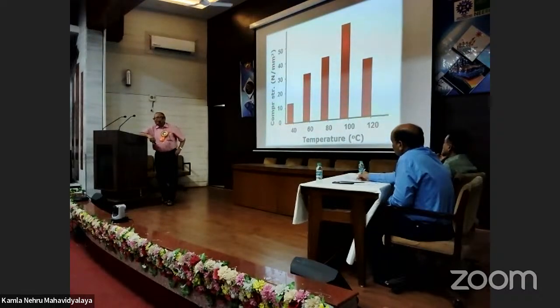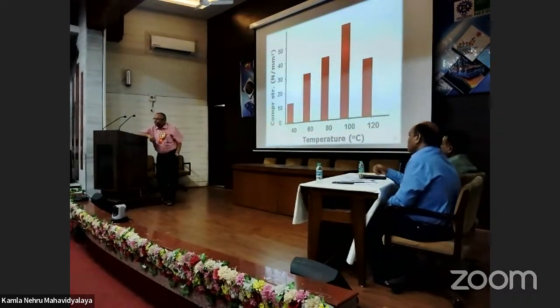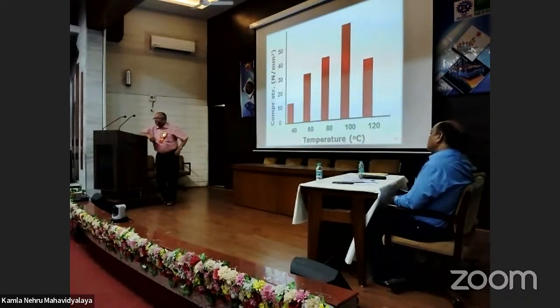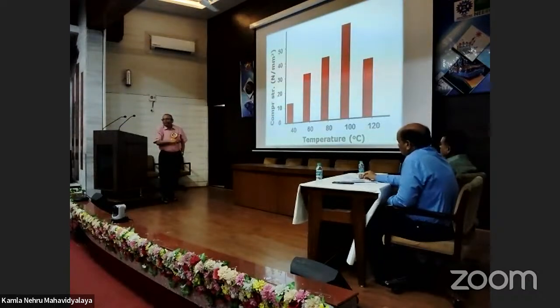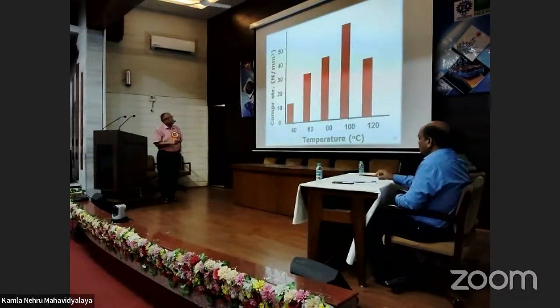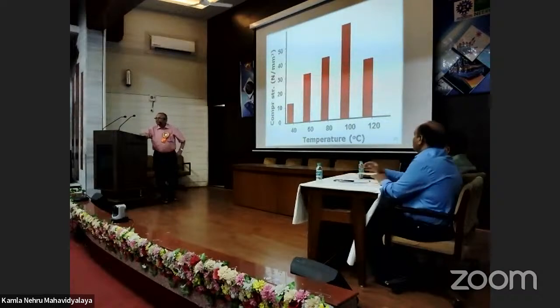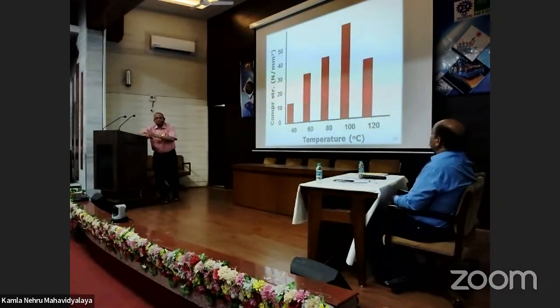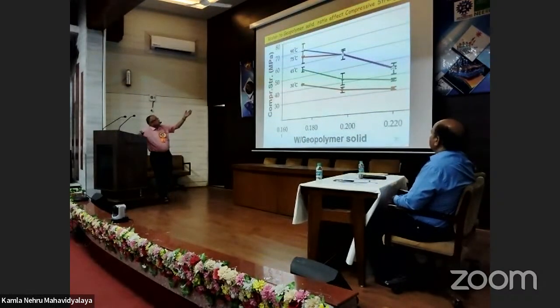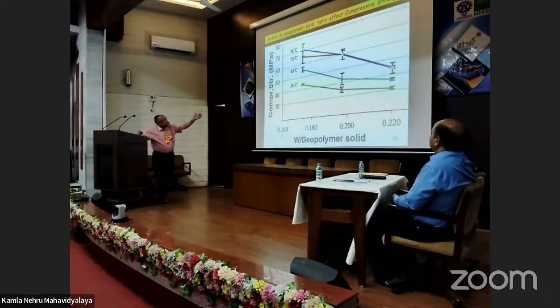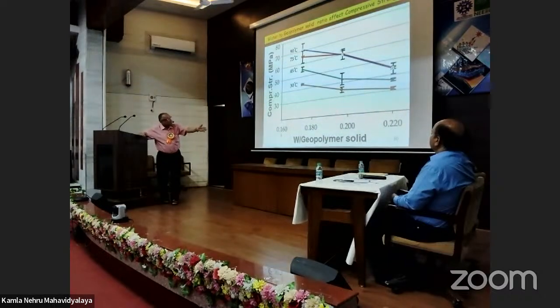100 degrees centigrade is the optimum limit. Above that, there is cracking and other things. Therefore, 100 degrees, or normally 80 degrees, is considered the curing temperature, for a few hours, maybe 24 hours. The compressive strength also changes with water solid ratio or water geopolymer ratio at different temperature. If you increase the water geopolymer ratio, the value decreases.